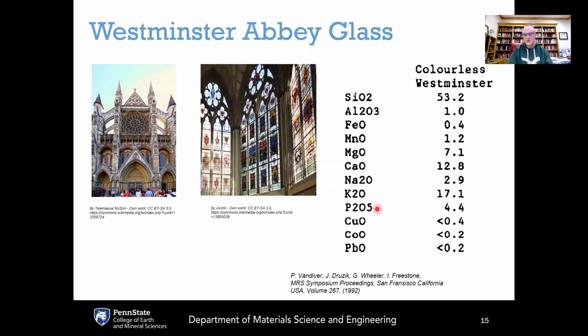Now, getting back to cathedral glass, one of the other things that was missing from that paper by Zanotto and Gupta is that they had used modern soda-lime silicate glass as a stand-in for the medieval cathedral glass, because that's where the data had been collected and published in the literature. But we wanted to go back and use an actual cathedral glass composition. Rather than taking glass from a cathedral, we made our own.